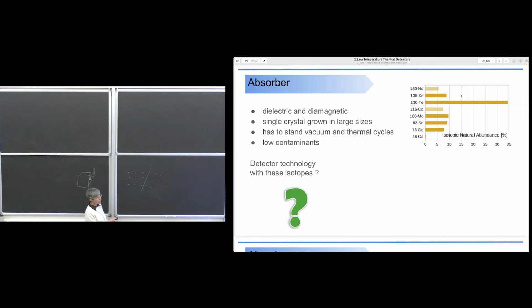On the other side, CUORE is using tellurium dioxide crystals. They can be as large as 2 kilograms. We are using 750 gram only because when we started the design of the experiment, 2 kilogram crystals were not yet grown by the Chinese producer that provided us the crystals. We tested them later, but it was too late to change the project. But in any case, it's a good absorber for tellurium, for a bolometer.